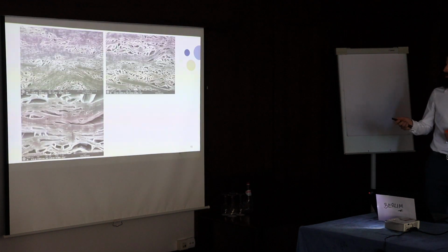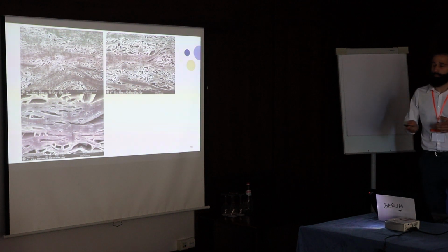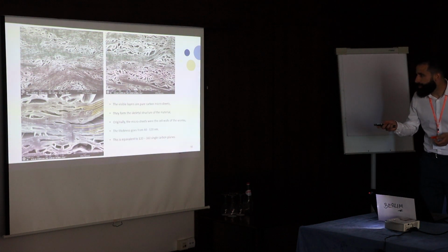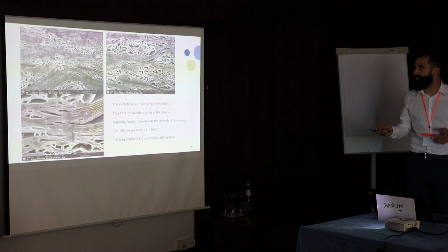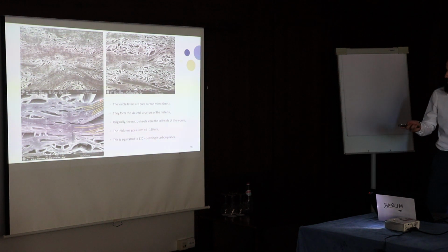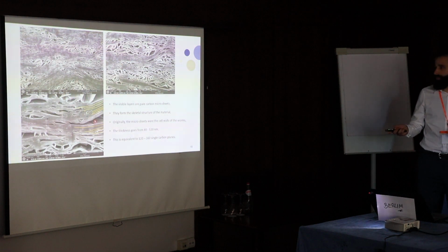This picture has a lot more information than the picture we had before. So finally we know how this material is made. If we go close, we see that it's a bit messy. There are a lot of pores of different sizes and different shapes. We can also see layers whose thickness is, on average, almost the same. These microsheets create the pore walls, and they are the skeleton of the material.